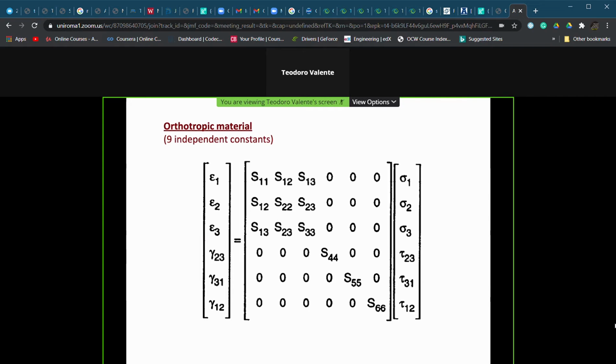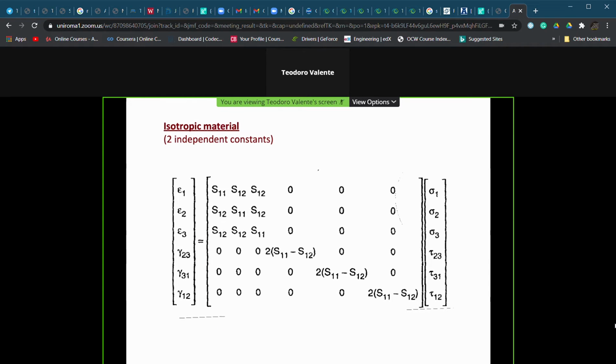So for isotropic materials, we can also write the compliance matrix, which is usually defined with the term S, and which you see, it's a matrix for which we are making a relationship between the strain and the stress. In this case, we need to change the terms inside the matrix, because the ones we have seen before were related to the calculation of the stress, known the values of the terms composing the strain tensor. So for orthotropic materials, again, we have 9 independent constants. For isotropic materials, again, there is no reason to change if we invert the relationship for independent constants. And these are the formulations of the compliance matrix.